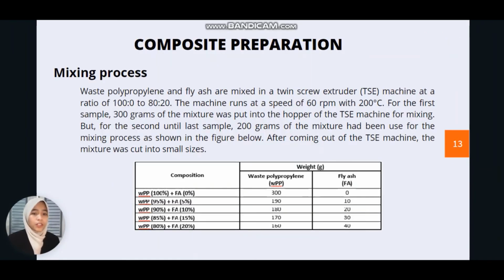So next is the composite preparation. So first, the mixing process. Polypropylene and fly ash will be mixed in the TSE machine at ratios of 100 to 0 and 80 to 20. The machine runs at a speed of 60 RPM at 200 degrees C. For the first sample, we use 300 grams of the mixture. We put it into the hopper of the TSE machine, while for the second until the last sample, we only use 200 grams of mixture because we want to save the mixture that we have. And then when the product has been produced from the TSE machine, it will be cut into small pieces.